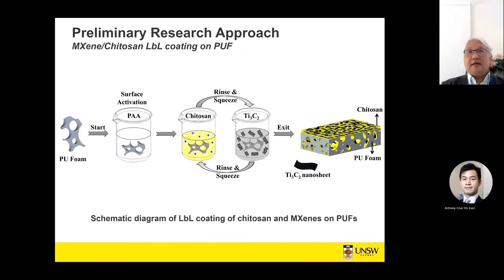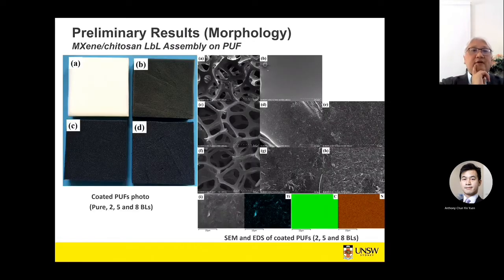As I demonstrate the layer-by-layer approach, we start with the foam, and then we surface activate using polyacrylic acid, basically to charge up the surface of the material. And then we do multiple layering between chitosan and Ti3C2. We cover this PU foam at the end of the day with chitosan and Ti3C2 with a number of layers.